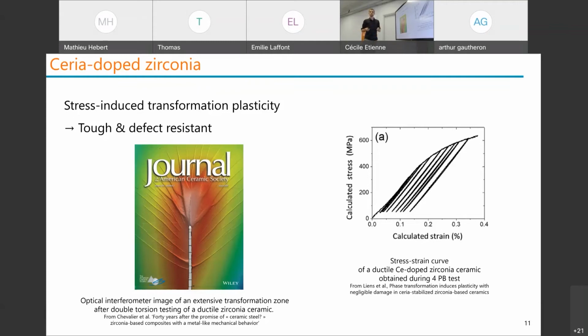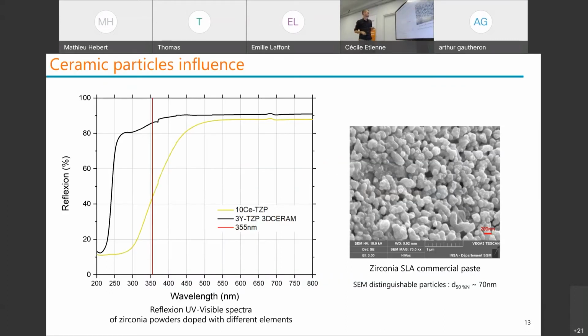And I told you that there exists commercial stereolithography paste, but not for this material. And we're going to understand together why. It's because of that. So here, my UV laser wavelength is in red. And you can see that at this wavelength, the commercial paste, which is in black, contains 3Y-TZP, so it's a zirconia more well known that is not very absorbent. So here you can see the difference with cerium zirconia, because of ceria-doped zirconia, because of the addition of cerium.